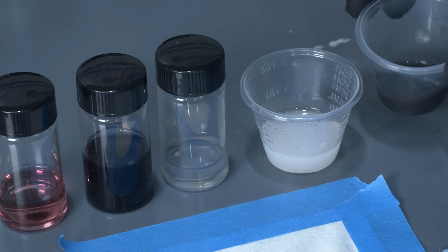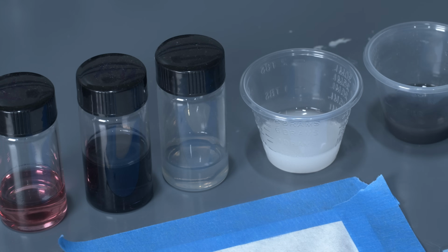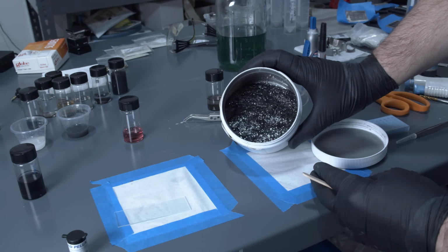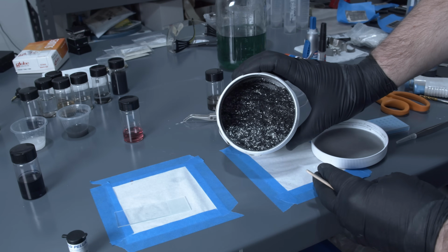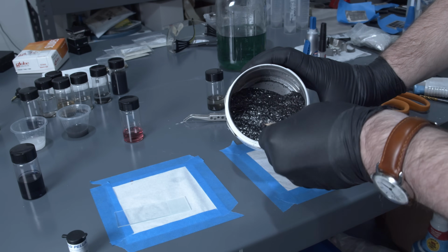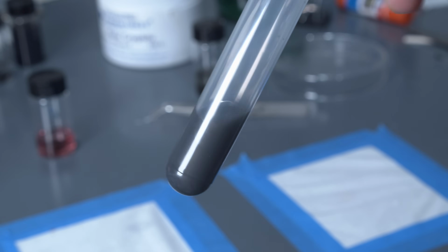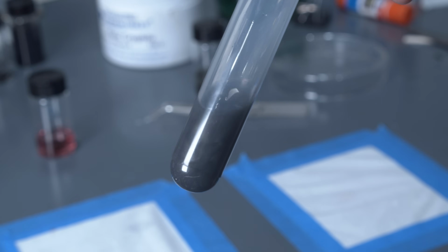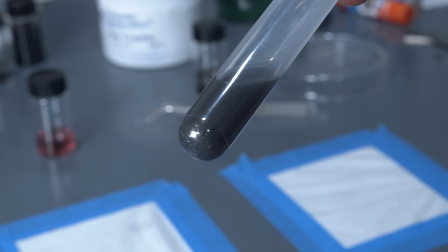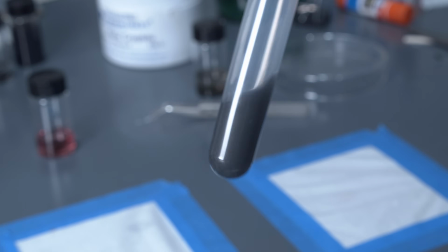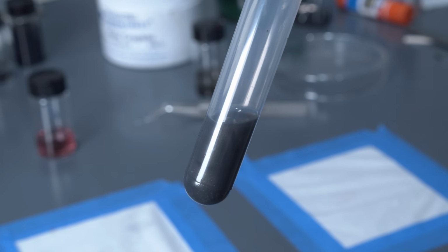And then also some tungsten disulfide. Again, 500 nanometers or less is what the label says. And then I took some flake graphite and threw it in the ultrasound for 10 or 15 minutes. This is kind of a classic way to exfoliate graphene monolayers. I don't expect that we'll be able to see the monolayers themselves, but we'll probably be able to see different layered graphites after this prep.